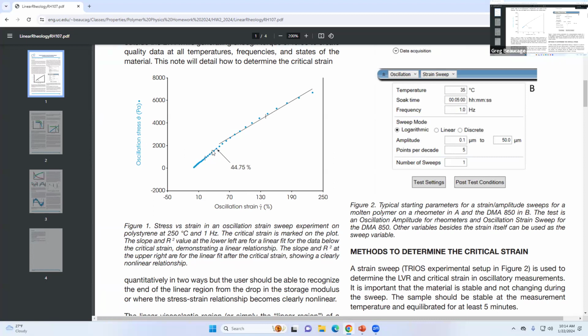So it just means you're at a low strain. This is strain amplitude. You're oscillating the strain, and there's a magnitude of the amount you oscillate, in percent. Usually you're operating at like 0.1 to 1% for this kind of vibrational rheology measurement.